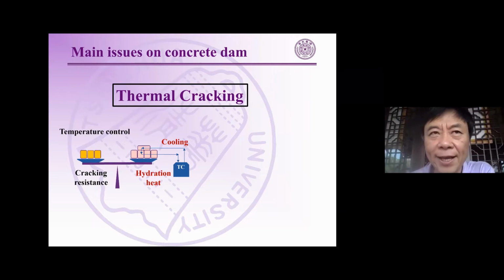And usually for concrete, especially for massive concrete like in a concrete dam, the cracking resistance and the hydration heat will make a balance. If the thermal stress from the hydration heat is lower than the cracking resistance, then temperature cracking will be prevented. But unfortunately, the hydration heat in massive concrete always induces higher thermal stress. So we have to use a temperature control method by cooling pipe.